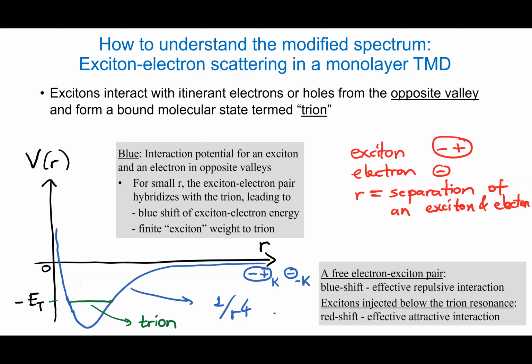And this, of course, rolls off and approaches a constant at very short distances. Such a potential in this case supports a bound state. Turns out that it's a single bound state. And that is what we refer to as the trion. So it's a bound state of an electron and an exciton.